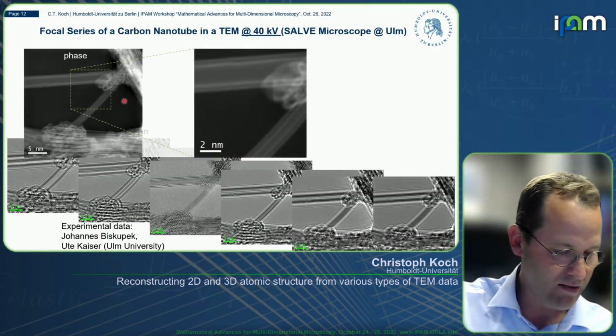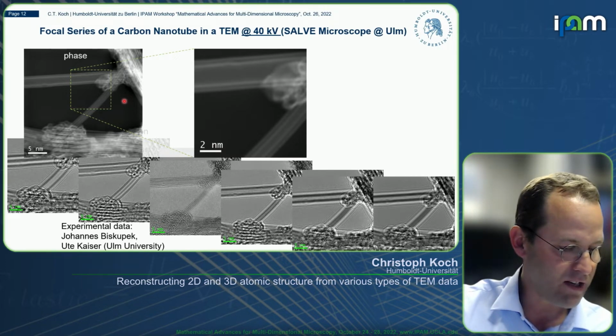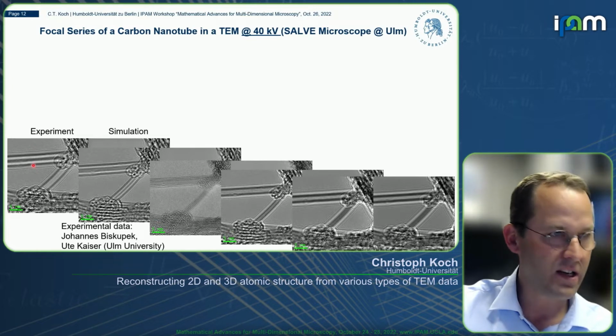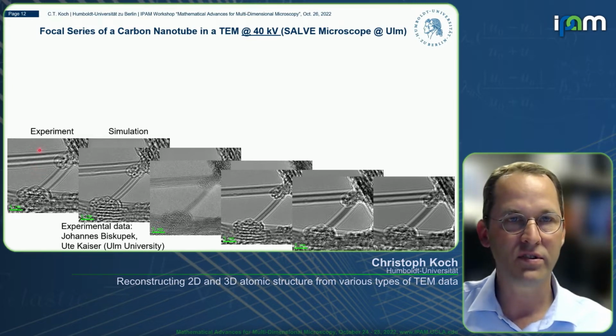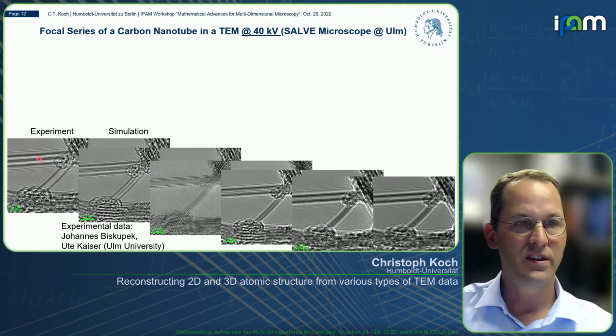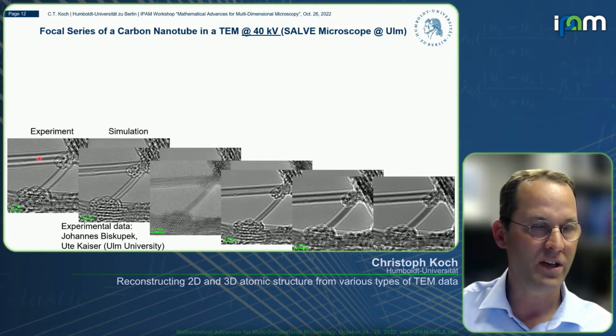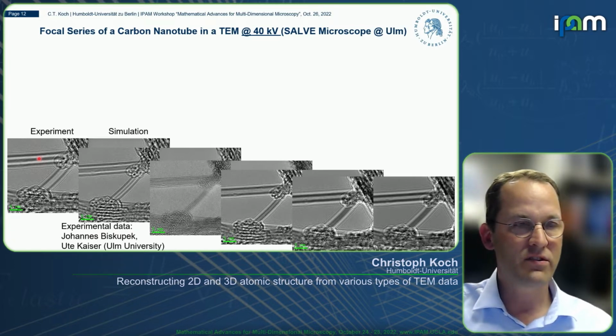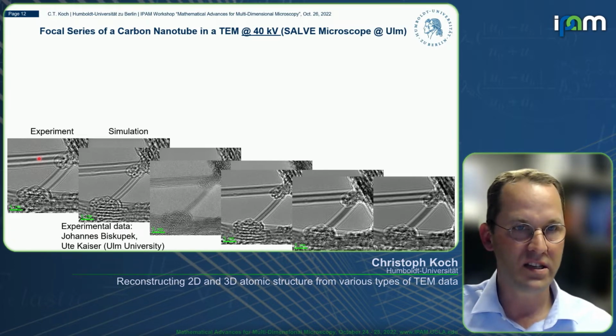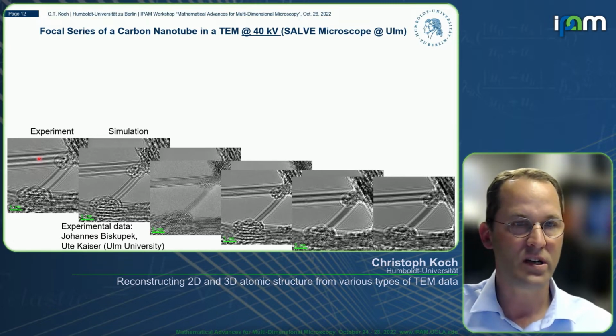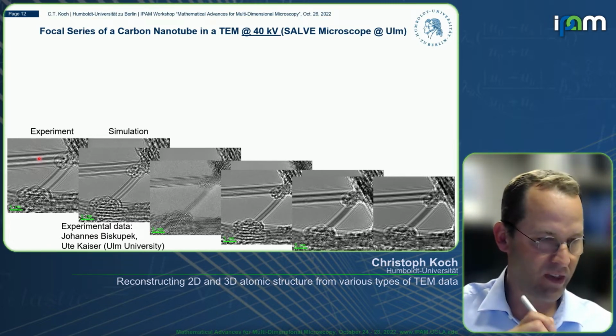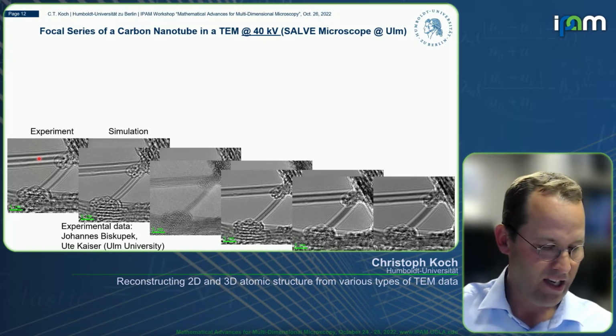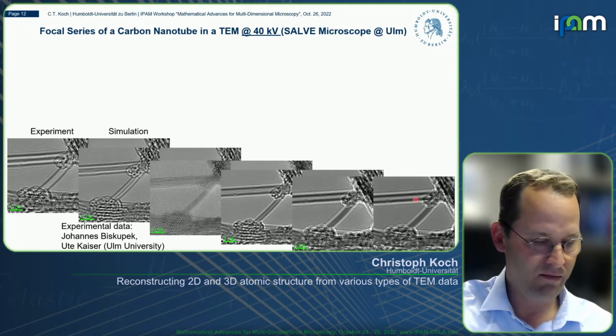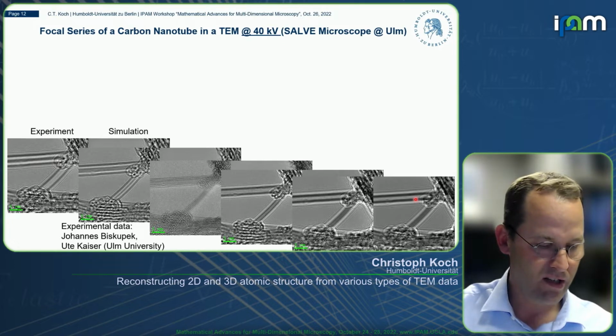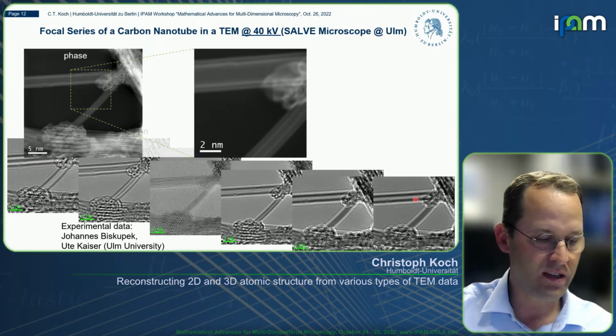From this focus series here, you can really see that because electrons are very coherent, you get large delocalization. But this delocalization is actually important in order to recover the phase shift of the electrons relative to, for example, the vacuum wave, but also to each other, because this nonlinear focus series reconstruction treats the interference between all the electrons that interfere with one another, not just interference with some undiffracted beam. And you can see now all this very convolved information can actually be recovered, and it recovers basically the phase shift inside the sample.